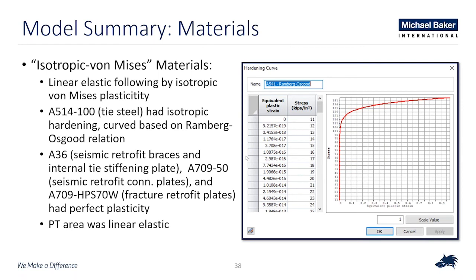For the rest of the steels, A36, A709 50, and A709 HPS 70W that were used in the retrofits, and then the A36 in the internal stiffening plates, we just use linear elastic with perfect plasticity because there weren't many spots that were getting even that close to yielding. And then the area where the PT forces are applied in the model was modeled as linear elastic. Not a lot of detail was really devoted in this local model to this. This was just to make sure that the forces were transferred adequately throughout the model without much distortion to the tie itself. You can go to the next slide.